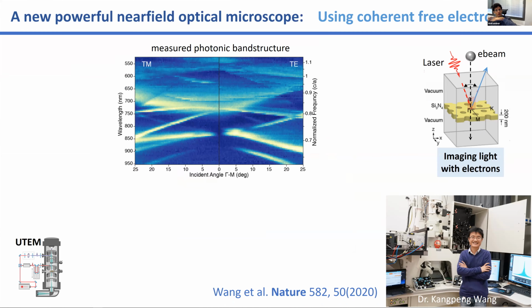And then we ask how strong the interaction is going to be by looking at the peaks of the EELS interaction. The stronger the laser field trapped inside, the more peaks we see in EELS, the brighter the point we put on this map. And then what I think is really wonderful, we see here in this map the photonic crystal band structure. It looks a lot like electronic band structures, but here, this is not for the electrons, but for the light modes trapped inside.